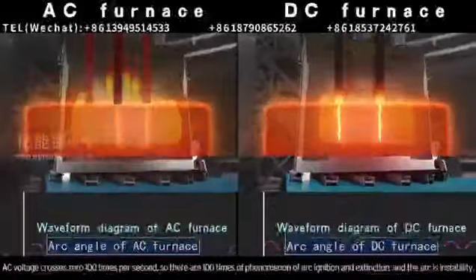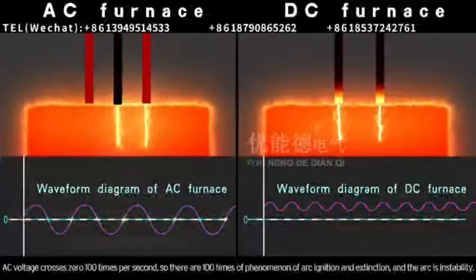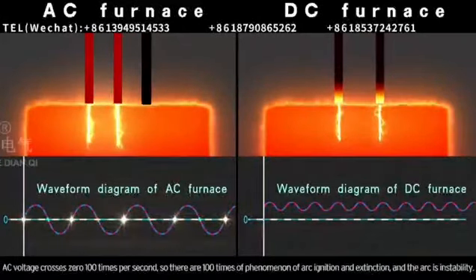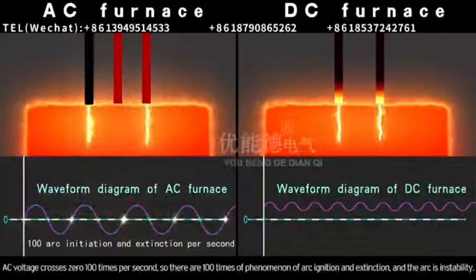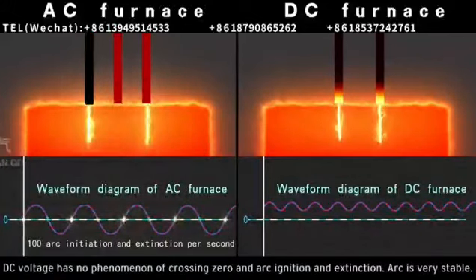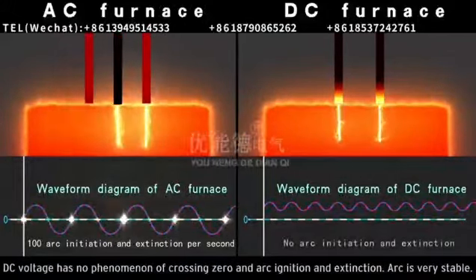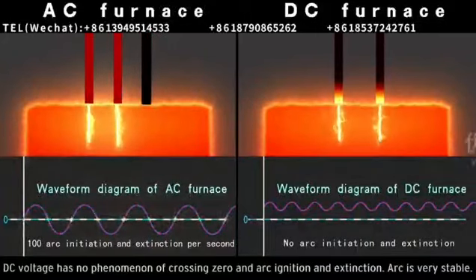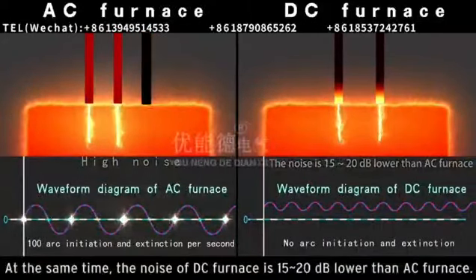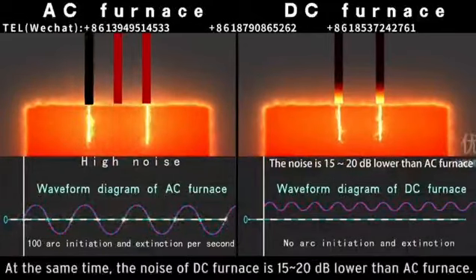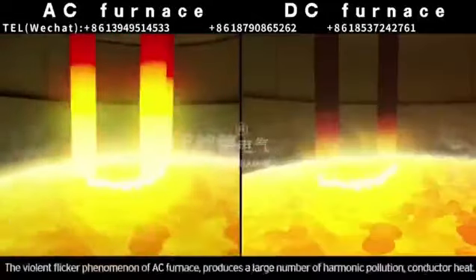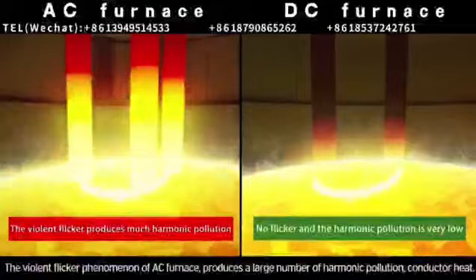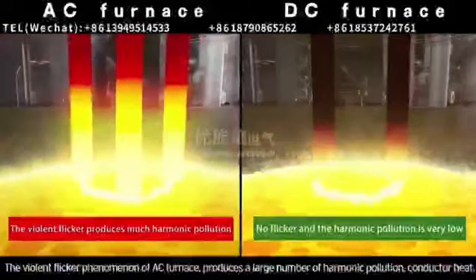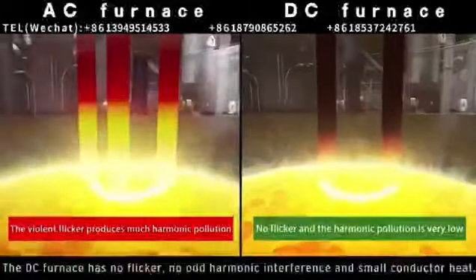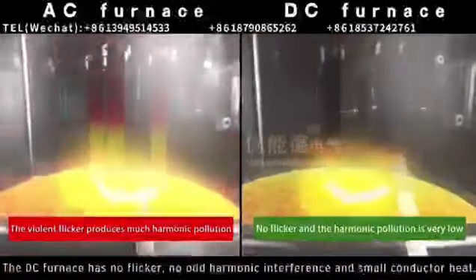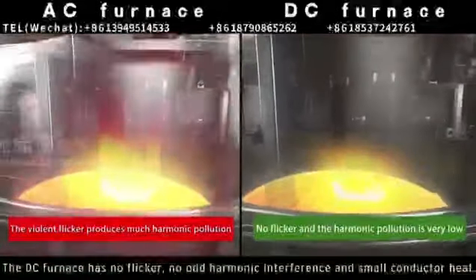AC voltage crosses 0 100 times per second, so there are 100 occurrences of arc ignition and extinction, and the arc is unstable. DC voltage has no phenomenon of crossing 0 in arc ignition and extinction. The arc is very stable. At the same time, the noise of the furnace is 15 to 20 dB lower than the AC furnace. The violent flicker phenomenon of AC furnace produces a large amount of harmonic pollution and conductor heat. The DC furnace has no flicker, no odd harmonic interference, and small conductor heat.